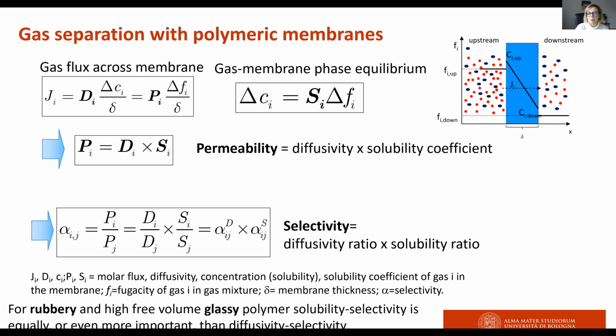In all membranes, you see a balance between the diffusivity-based contribution, which favors the smaller penetrants, and the solubility one, which usually, but not always, favors the larger penetrants. In the case of CO2, this mechanism is a little bit reversed, because CO2 is considered generally a small penetrant with respect to many other ones, but is normally highly soluble in polymers. In general, for rubbery and glassy polymers and high free volume glassy polymers, the solubility selectivity can be equal or even more important than the diffusivity selectivity.